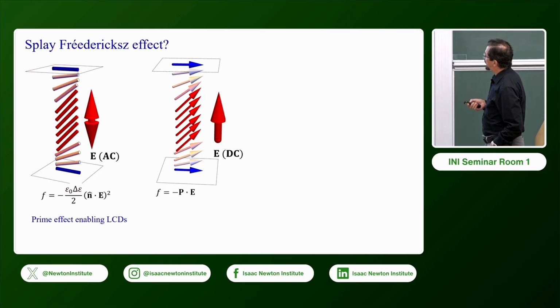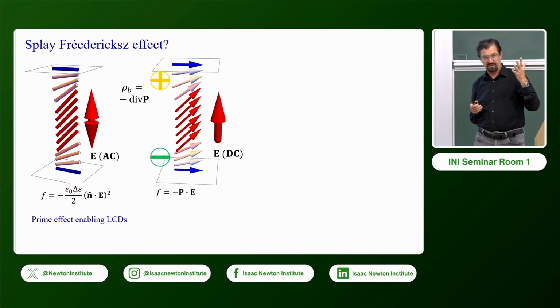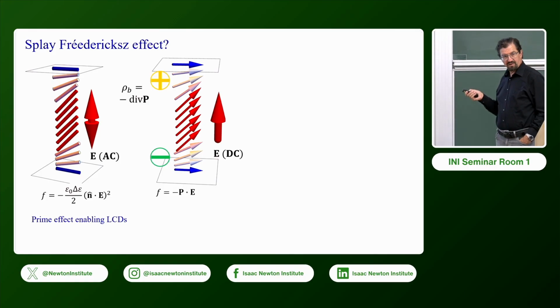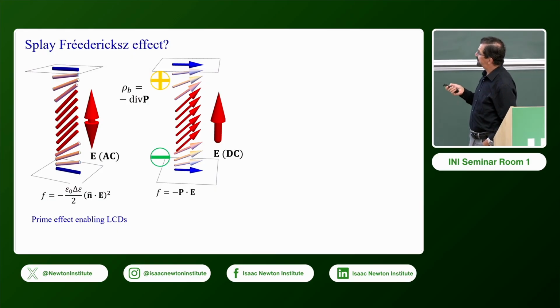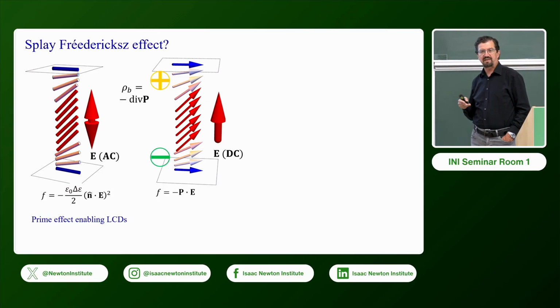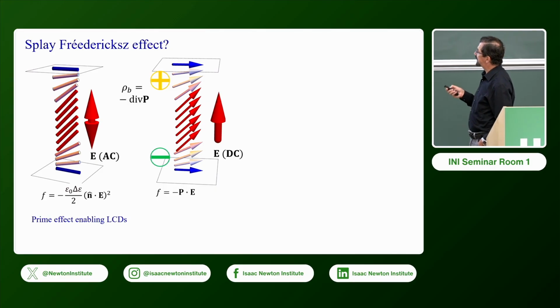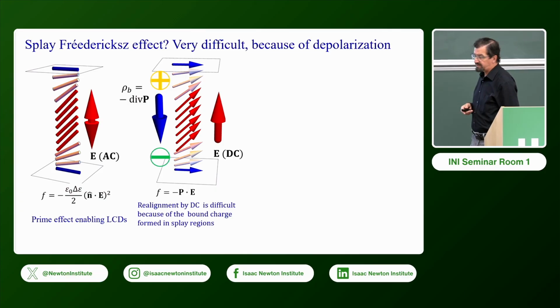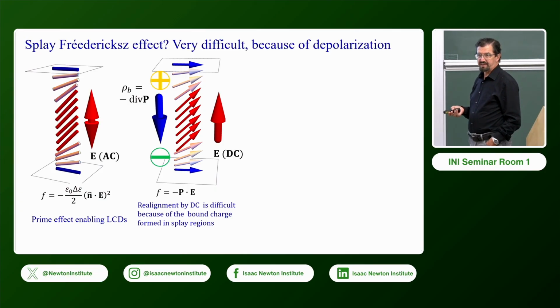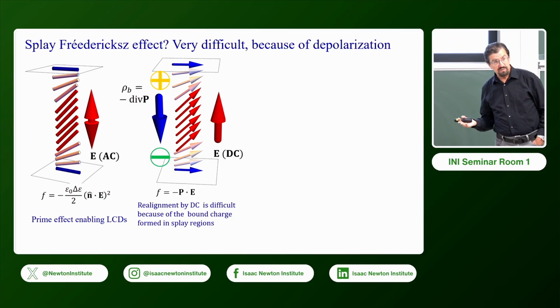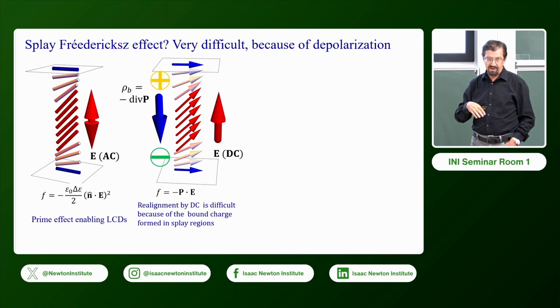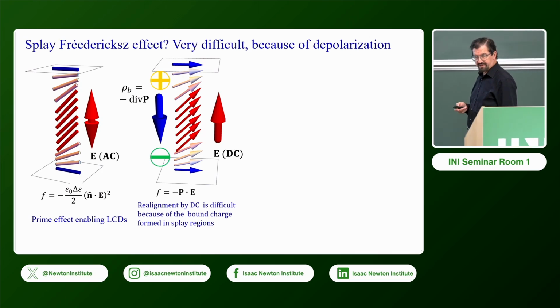And if I would consider a similar situation in a ferroelectric nematic, then I would realize that near the top and bottom electrode, I would have a splay deformation, because the surface anchoring at the plates would keep the polarization horizontal, and the electric field would try to realign it along itself in the bulk. So I would have splay in those two regions. And of course, the splay would create the polarization field that would oppose the externally applied field and will try to realign the polarization back.